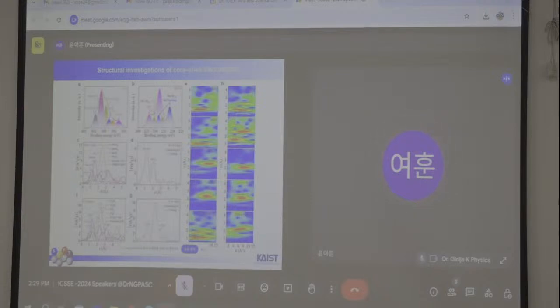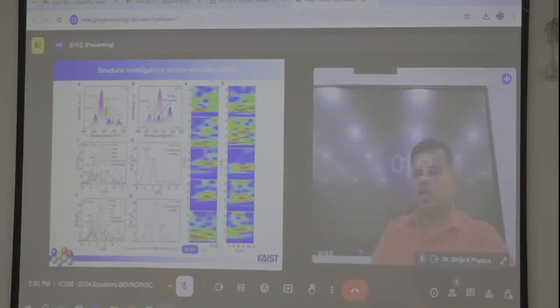So this is pyrrolic molybdenum rather than pyridinic molybdenum in this case, and the molybdenum has different phases like 4+, 6+, and the nitride phase is also available. It may be confirmed by the molybdenum-nitrogen bonding. I previously told you that XANES analysis is one of the important techniques to predict the molybdenum bonding nature, because the local structure is predicted from the XANES and EXAFS analysis.